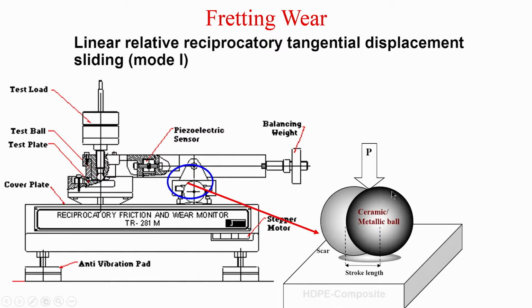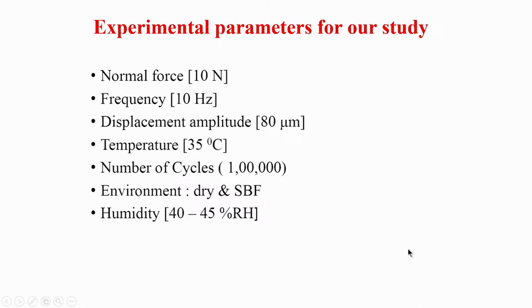So, this cartoon was already discussed in an earlier lecture: you have a ceramic or metallic ball, there is a relative displacement, and this is called the stroke length. The stroke length in case of fretting wear varies somewhere between 100 and 200 micron. These are the high density polyethylene, hydroxyapatite and alumina composites which are used with different compositions as flat materials.